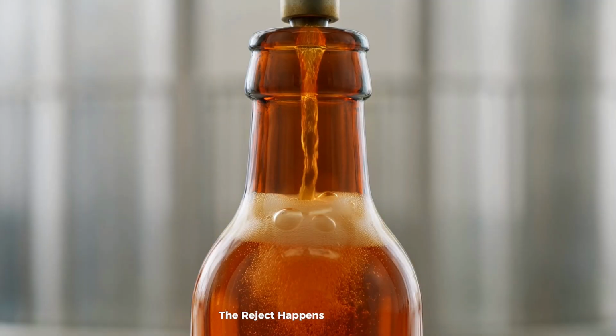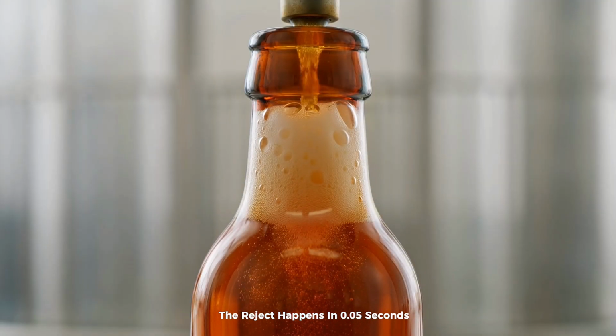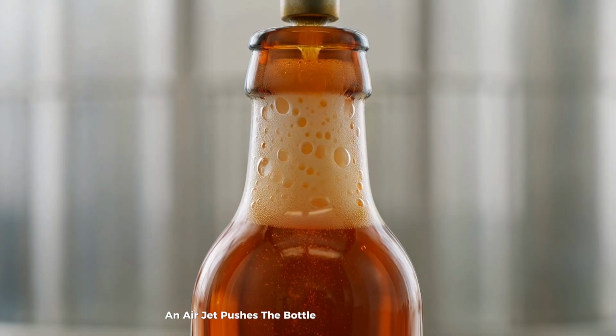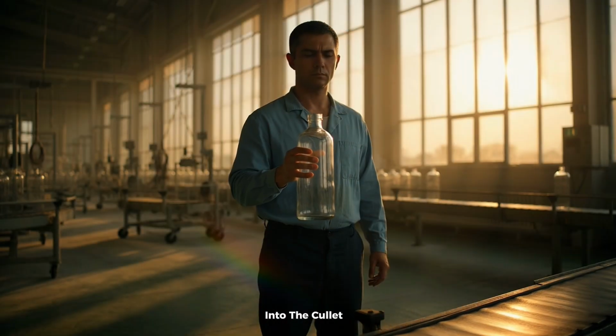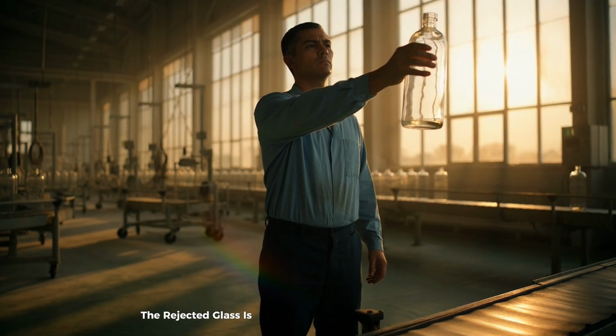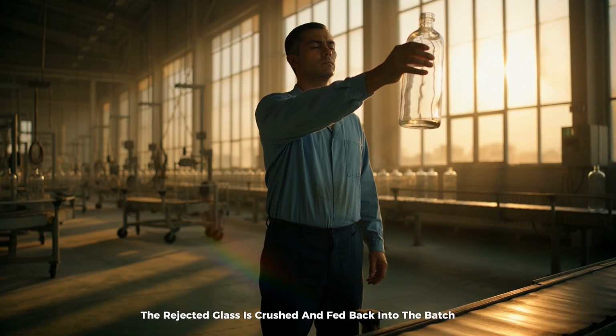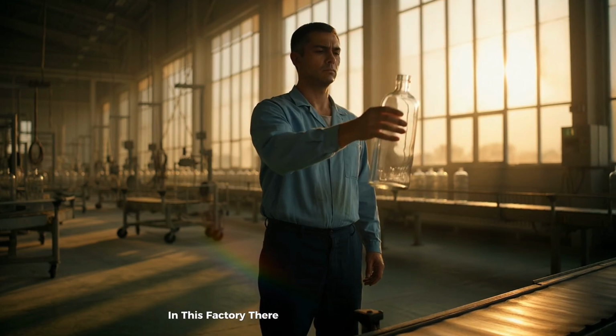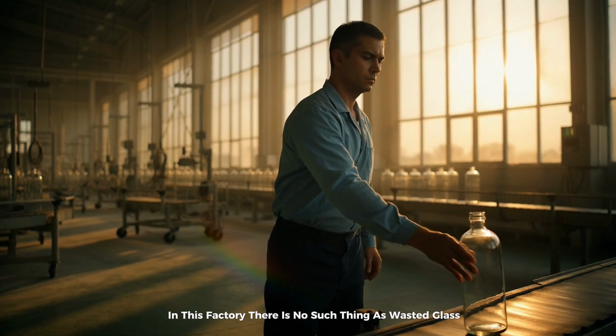The reject happens in 0.05 seconds. An air jet pushes the bottle sideways off the conveyor into the cullet bin. The rejected glass is crushed and fed back into the batch mixer. In this factory, there is no such thing as wasted glass.